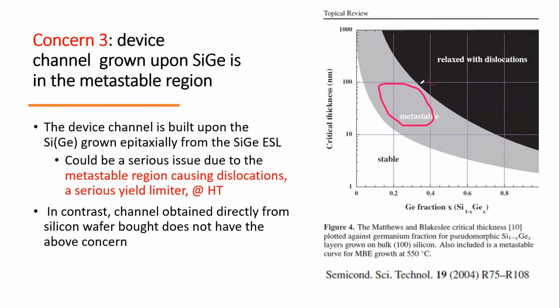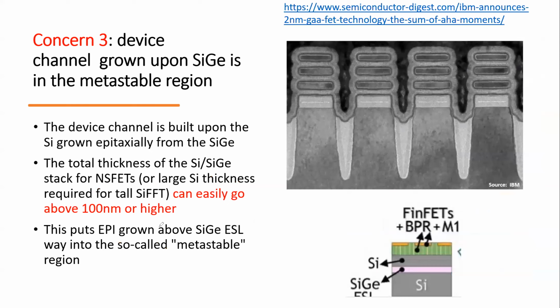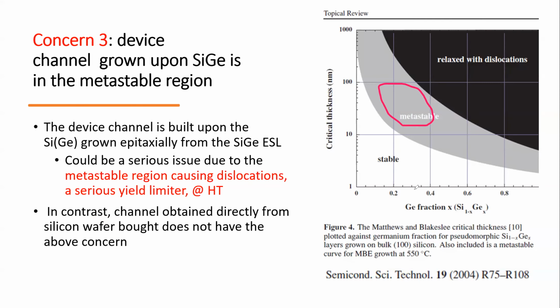then the epitaxial quality will be bad. You will be full of dislocations. But if you grow only, say, 5 nanometers, you're fine. No matter what you do, it's very stable. But unfortunately, you need a very thick one, right? You need some 100 nanometers. And then what's the range of germanium? Probably in the 20 to 30%. Okay, so you are fine.